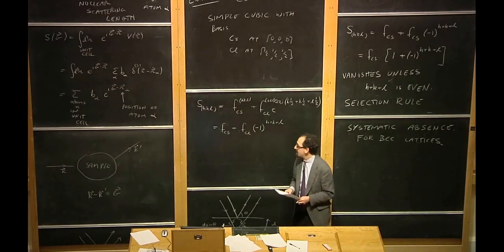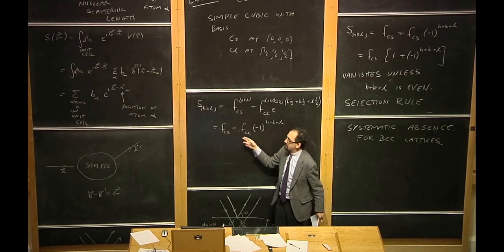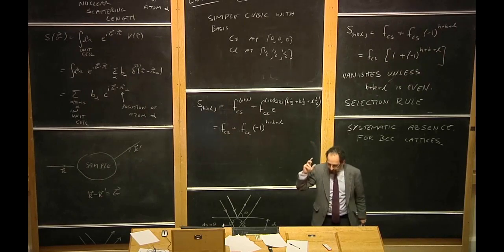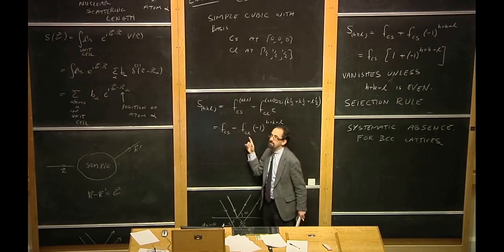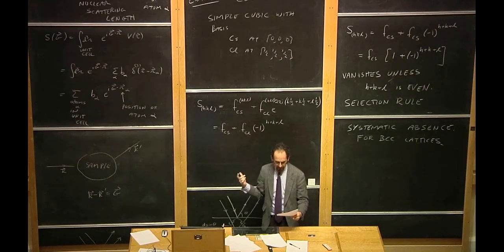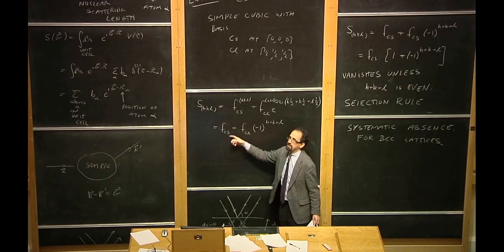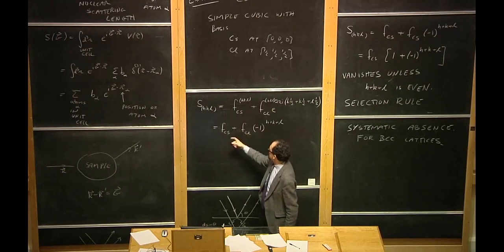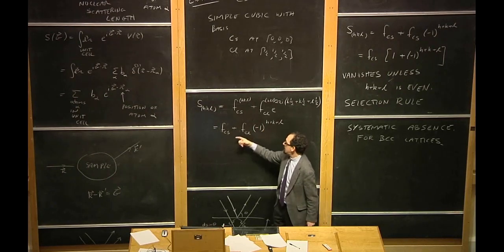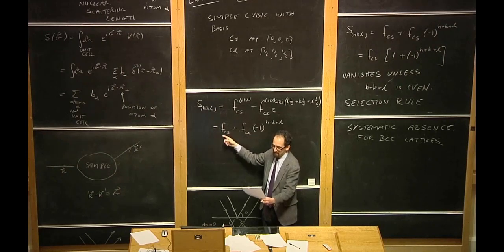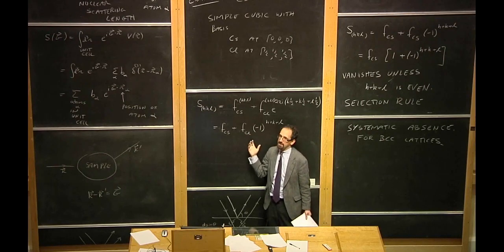Potassium chloride is a very good guess, and the reason potassium chloride is a good guess is because remember that these form factors are basically proportional to the atomic number. And the atomic number of cesium and chlorine are extremely different. Chlorine is number 17, and cesium is number 55. So these two numbers will be extremely different. But if you replaced the cesium with potassium, which is right above it on the periodic table, so it's chemically very similar, then potassium has atomic number 19 and chlorine has the atomic number 17. So these would be pretty close to each other, and you'd have a near cancellation.